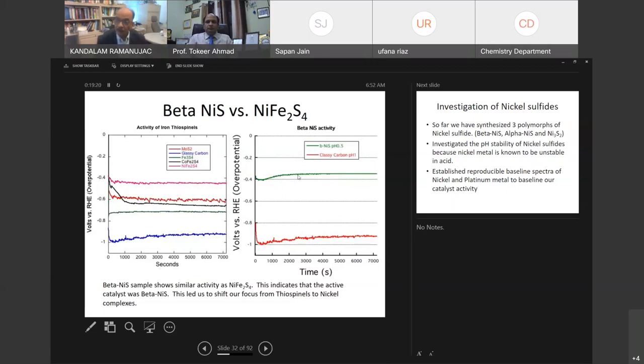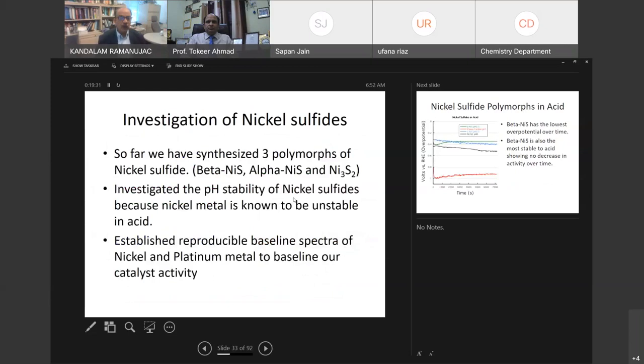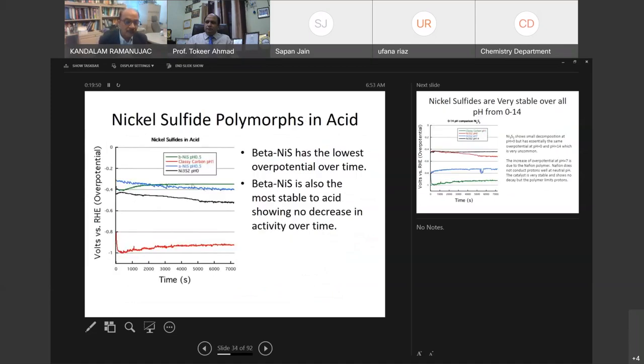Then we thought, well, these nickel sulfides have never been reported in the literature to the detail that I'm showing you here. So what other phases of nickel and sulfur might be interesting? Then we looked at phase diagrams. There's a beta form of nickel sulfide, there's an alpha form of nickel sulfide, and there is also Ni3S2 that is also known in the literature. So we said, why not check those to see if any of them show superior activity. Comparing them, the Ni3S2 shown in black is not as good, and the alpha form of nickel sulfide is also not as good.